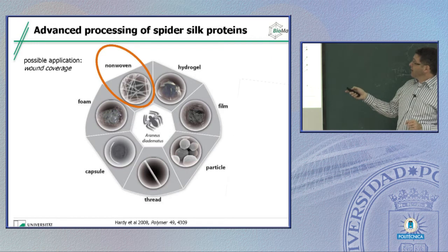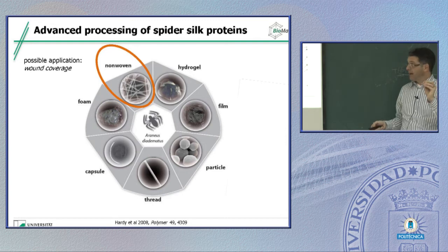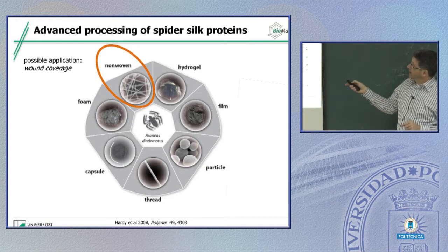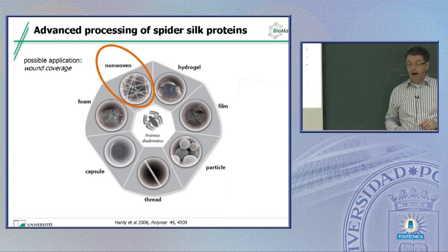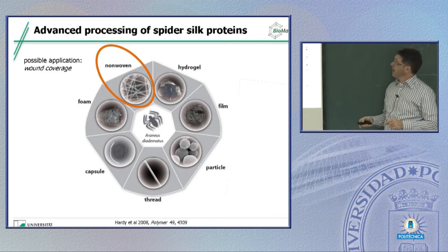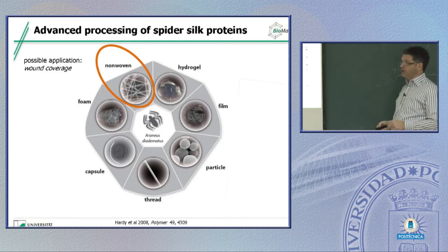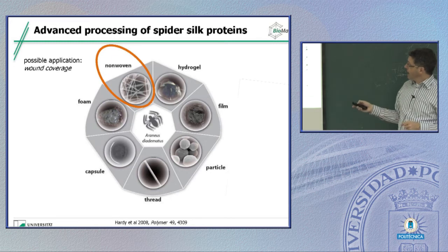And the number down here just gives you the diameter of the fiber. 150 means the individual fibers have 150 nanometers in diameter. 250, 480, 680 respectively give you the diameter of the fibers, and you can see here that there is a strict dependency on the fiber diameter. Fibers with roughly 700 nanometers in diameter show a very good cell adhesion, and it's as good as the control, and the control is a tissue that is optimized for fibroblast adhesion.